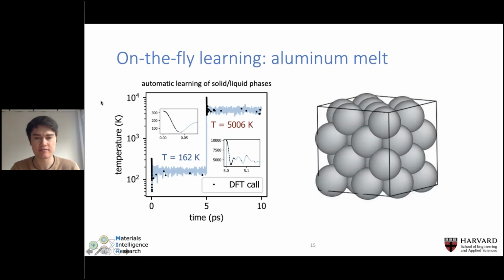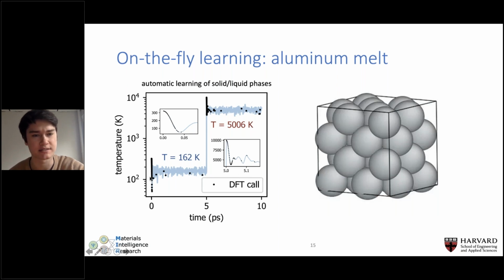So that's the general theoretical framework. In the second half of the talk, I'll go through a few examples of different systems that we've applied this approach to, starting with a toy example. Here we have a 32 atom supercell of aluminum, and we're initializing the system at a fairly low temperature in the FCC phase, around 100 to 200 Kelvin.